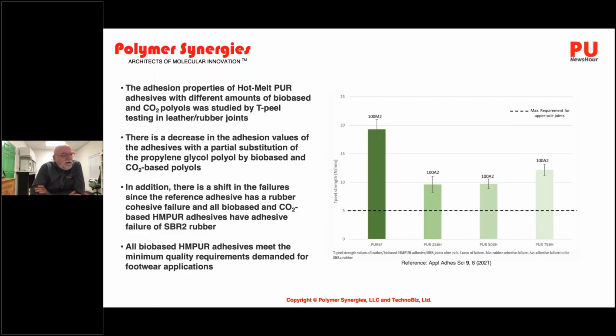They have some physical property data here, looking at the adhesion properties via a T-peel. We can see that there are different amounts of these bio-based and CO2-based polyols that were used in leather to rubber joints. And this is the polyurethane reference. You can see that these materials here have less T-peel strength. However, they do exceed the maximum requirements for these types of joints. In addition, the article talks about a shift in the failure mode. So although the strength may be lower, strength isn't the only overall criterion that should be considered for designing an adhesive. You have to think about all of the factors that you want.